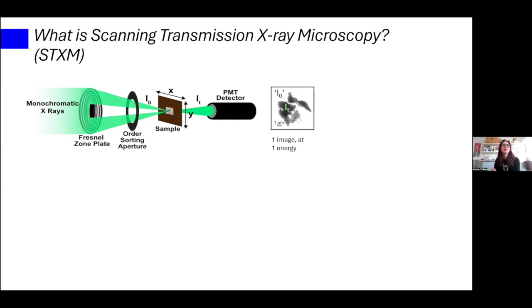Obviously, where there is a sample, where there is something on the plate, let's say, less light will be transmitted, so it will look darker. Places where there is not something will be relatively intense and white, because that is where the beam just basically travels through unhindered. We use that as a calibration. If you have empty bits on your sample area, we call those I0. The transmitted beam is whatever goes through your sample, and therefore intensity is taken out because X-rays are absorbed by your sample. So this is a pixel by pixel image that is built up at one energy.